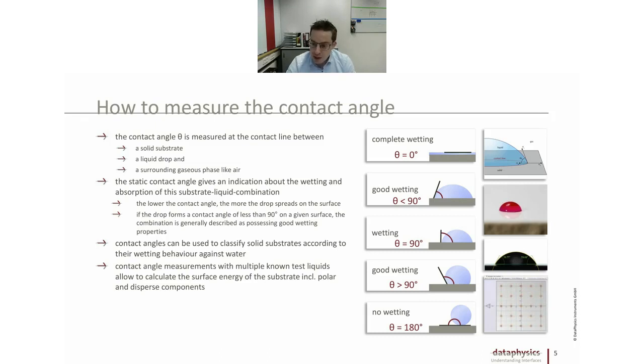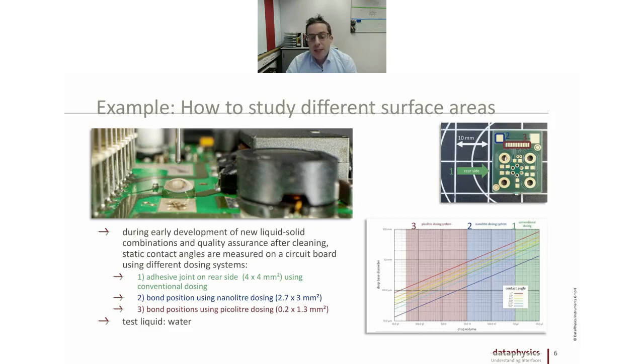So this means from the picture seen from the side of the droplet on the solid surface, we can basically quantify how well wettable the surface is. And from these wettability parameters, we can, for example, calculate the polarity of the solid surface. You can then judge whether a plasma treatment was successful or not. Plasma treatment makes the surface more polar. You can judge whether a coating was applied successfully and probably even whether your sputtering process was successful or not. So it's applicable basically in any field you can imagine. I want to show you now with a little application example what is possible with modern technology.